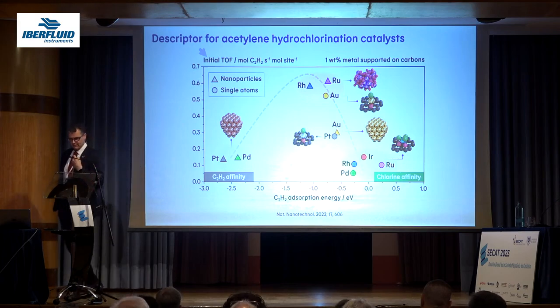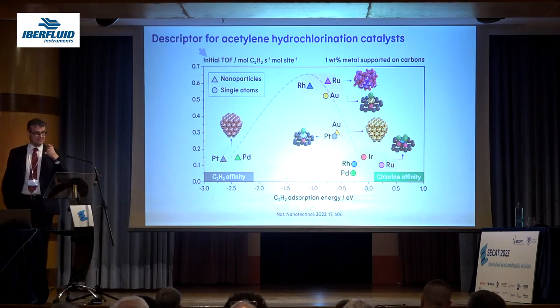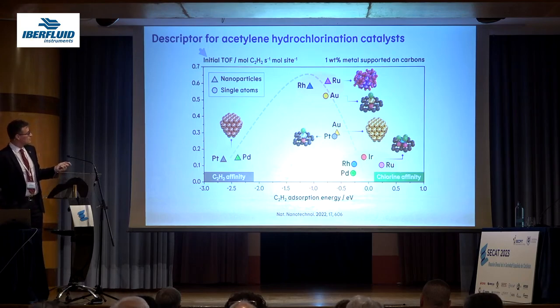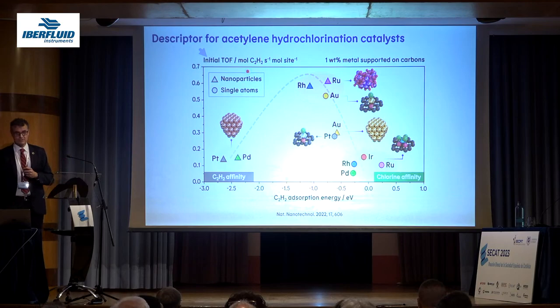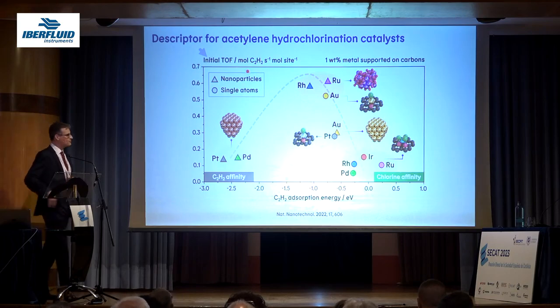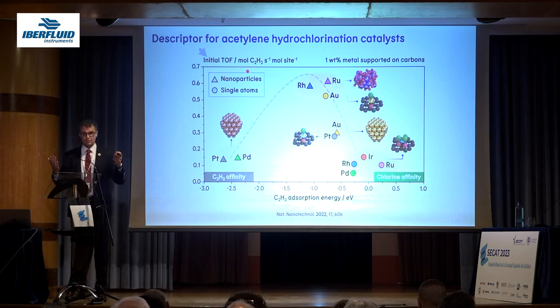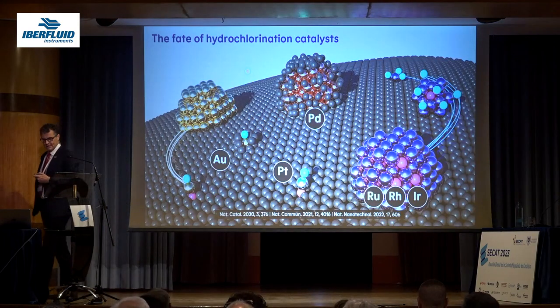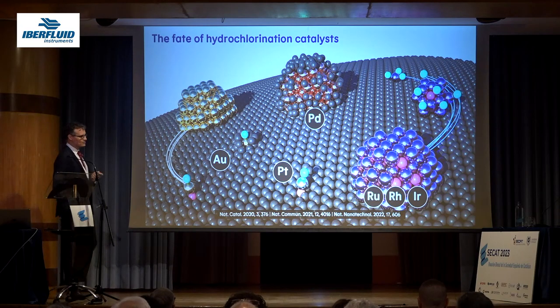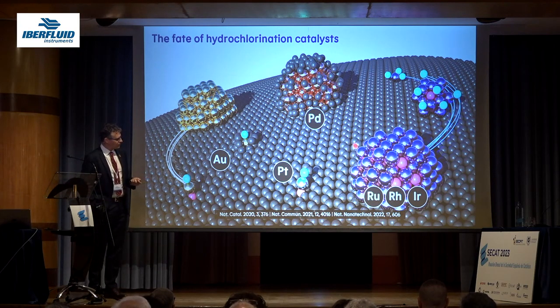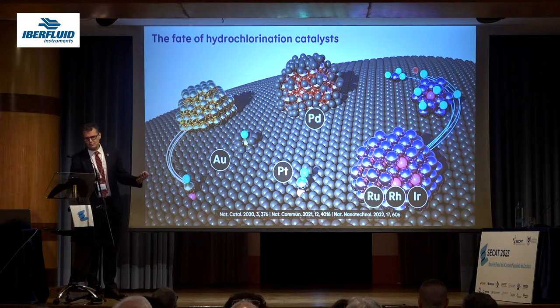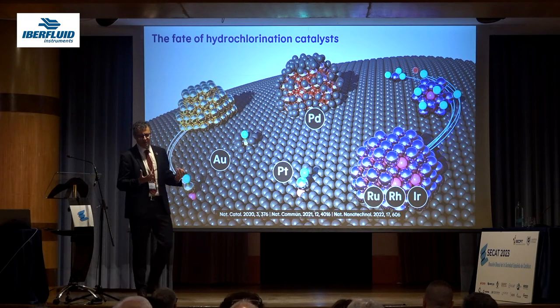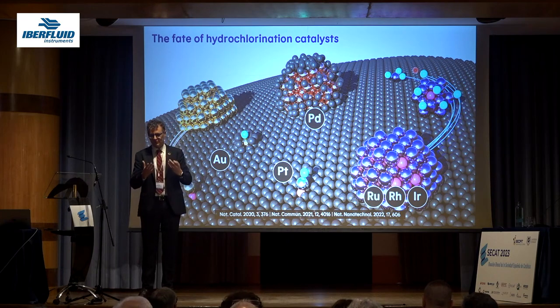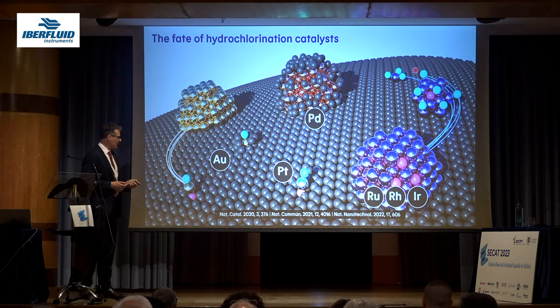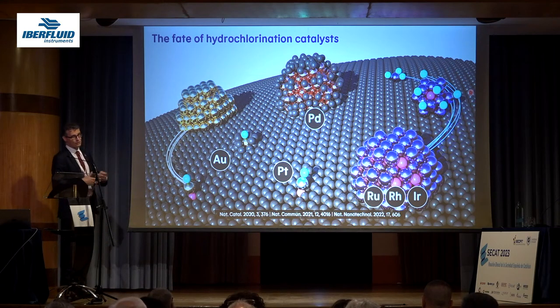Again, for the sake of what I said before, are these materials stable? Because all these correlations are derived for initial turnover frequency, few minutes on stream, right? But you would like to know if these survive hours on stream or thousands of hours on stream, right? And indeed, what happens is that most of these nanostructures are not stable. So these beautiful rhodium and ruthenium nanoparticles during reaction conditions will redisperse on the support, forming single atoms. Single atoms of these metals over-chlorinate, so the activity is set to 0, while gold has the ability, very nice ability, to sinter.